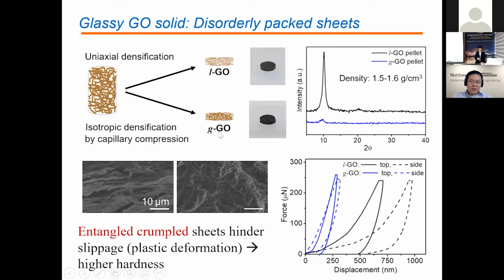For the other sample, we first wet this with a moisturizer, with a handheld beauty spray. And then we let it dry in air, and this creates a much more isotropic compression force field. So in the end, you're generating a pellet. Now we do have to slightly adjust the shape using a very gentle compression, just so that the shape matches. But the pellet still is largely disordered, because it lacks the long-range stacking here. And this can be seen in X-ray diffraction.